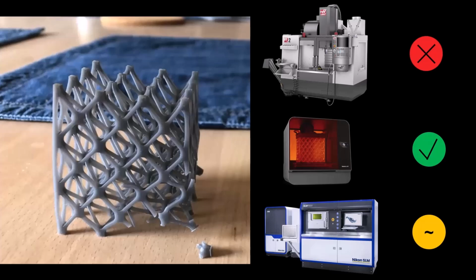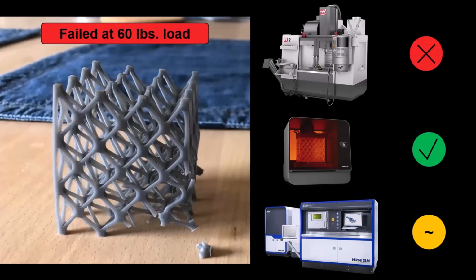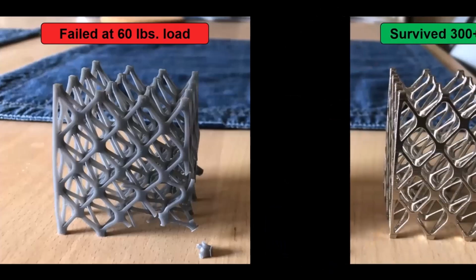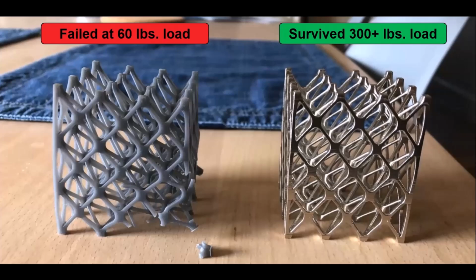Problem is, this lattice has to bear the full weight of a human. In Tough 2000, one of Formlabs' most popular engineering-grade resins and an ABS mimic, it didn't survive, failing at about 60 pounds. So, how can we increase the strength without changing tech or the base material? Well, we can electroplate it. After plating with majority nickel and some copper, the lattice was bearing 300 pounds without failure.